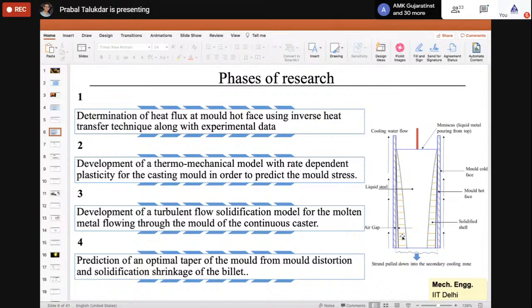This is called a shell because it is only at the outer periphery. This gives you a solid boundary, and inside that you have liquid metal. Initially you have only a solid shell in the beginning, and then gradually everything becomes solid. That takes some time. And if you see here, there is an air gap. The white color shown here is an air gap.